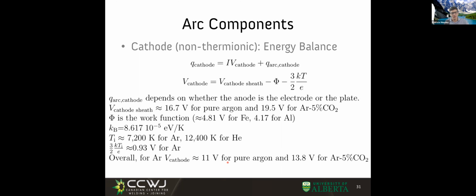The cathode, the thermionic cathode, is more or less 1 volt. So the voltage times current gives us power, so lower voltages means lower energy. And in the anode, we have 4.5 volts that help us melt the anode. In tungsten, we have more or less 1 volt that hopefully does not melt our cathode. But then in a non-thermionic cathode, that is the case, for example, of MIG, we have 11 or 13.8 volts in the cathode.